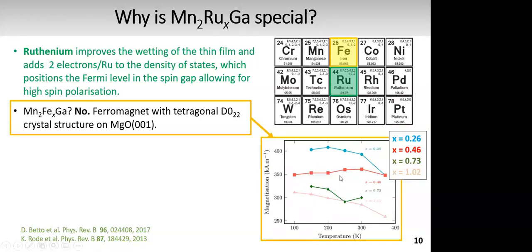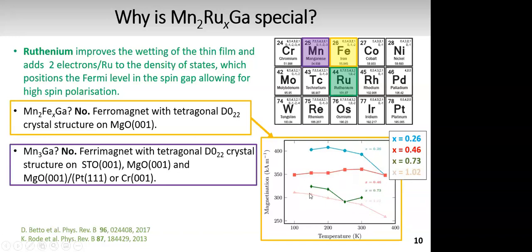And on the right hand side, I'm showing some magnetization curves. So it's magnetization versus temperature, showing the typical ferromagnetic behavior. Then another choice would be put in another manganese. However, that is also not a zero moment half metal. It's a ferrimagnet that crystallizes in the tetragonal DO22 structure on various different substrates that I've listed on my slide.